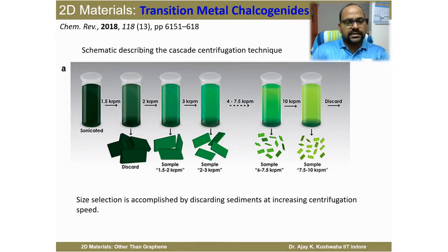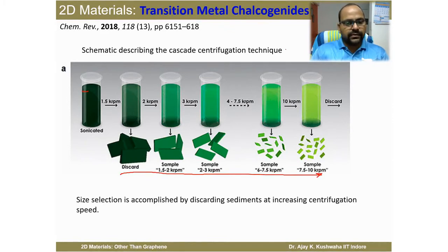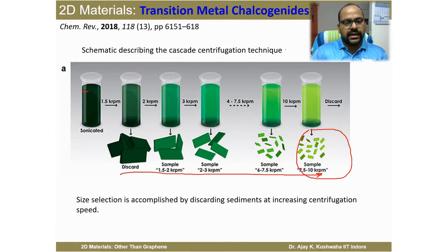Another simple but very useful experiment demonstrated control of centrifuge speed after sonication to separate the sheets. By changing the RPM from 1.5k to 10k RPM, beautiful differences in sheet size were observed. At 1.5k RPM, very thick and large sheets are obtained. As the RPM increases — 3, 4, 5, 7, up to 10k — very thin and small sheets of transition metal chalcogenide are obtained. Just by adopting this strategy, we can control both thickness and size of the sheet.